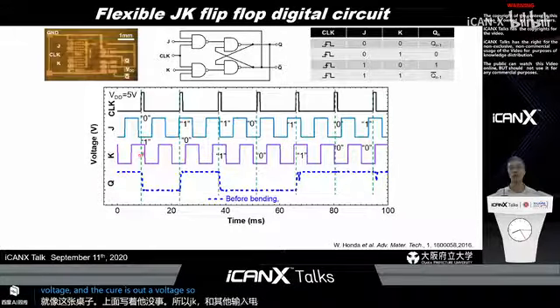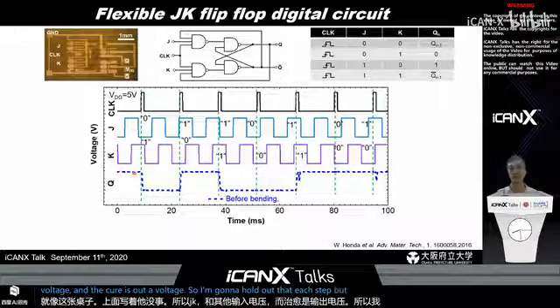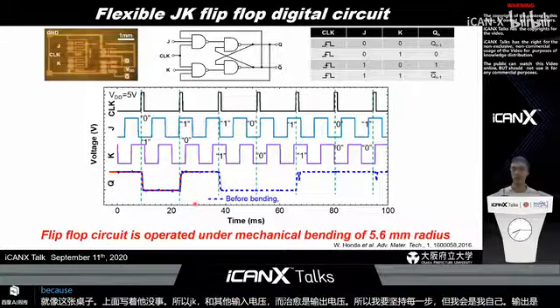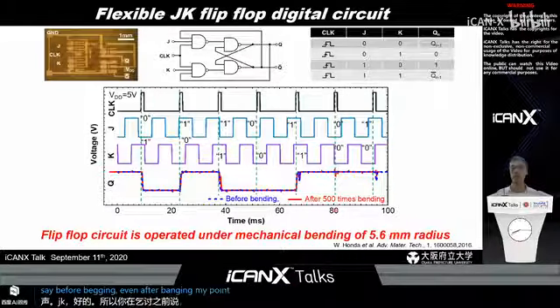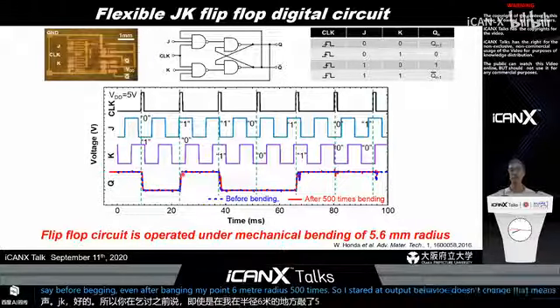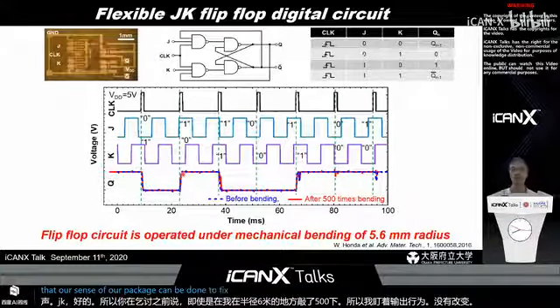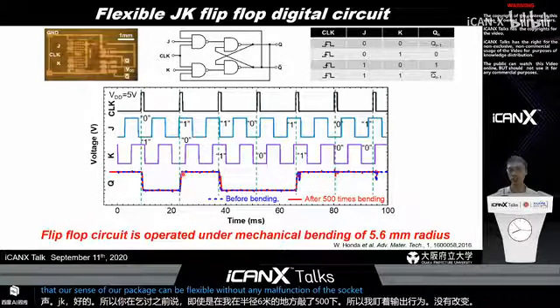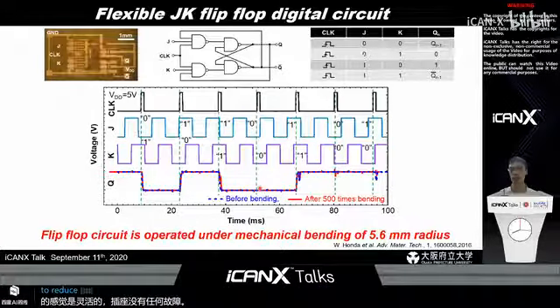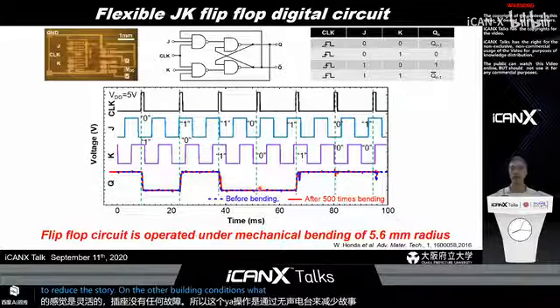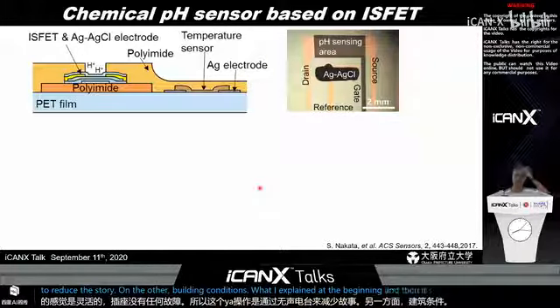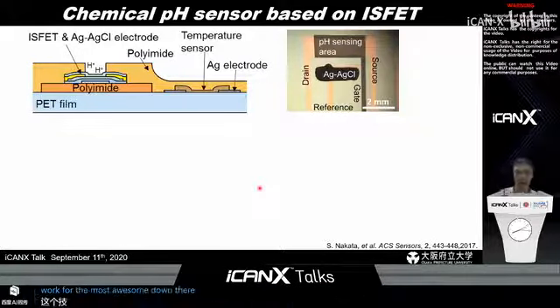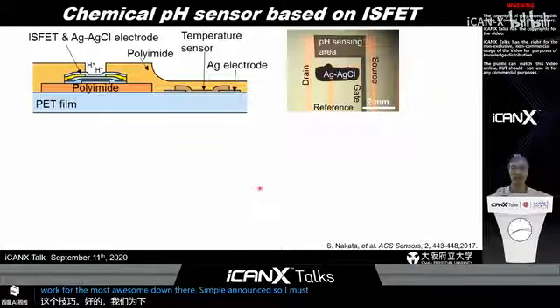I cannot follow each step, but please believe me, the output operates well as a JK flip-flop circuit. This is before bending, and even after bending at 5.6 millimeter radius, after 500 times, the output behavior still doesn't change. That means our circuit can be mechanically flexible without any malfunction of the circuit. This reliable operation is realized by the passivation layer to reduce the strain under the bending conditions, which I explained at the beginning. Using that technique, we also demonstrated some very simple analog circuits. However, I must skip the result today.